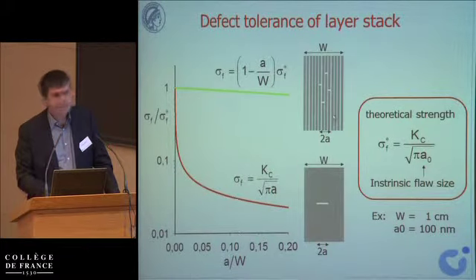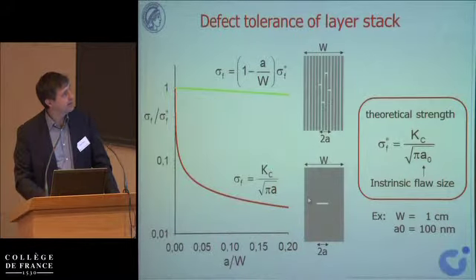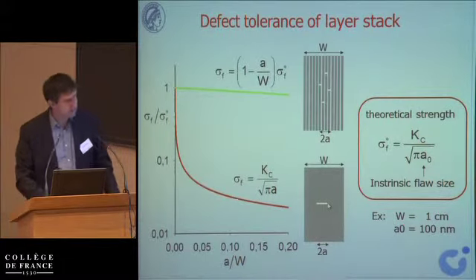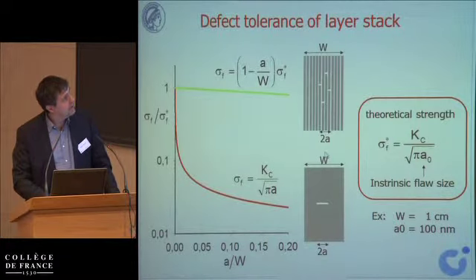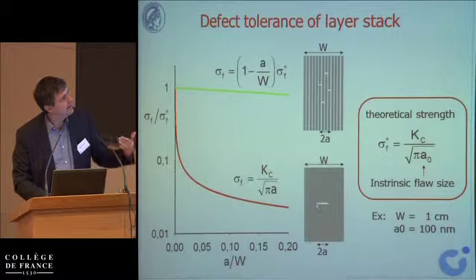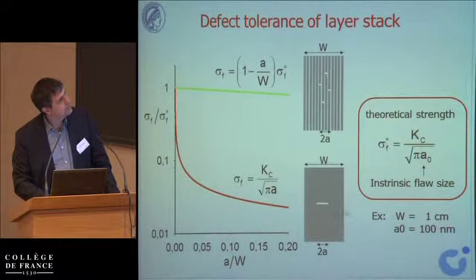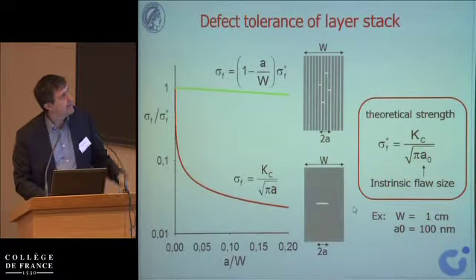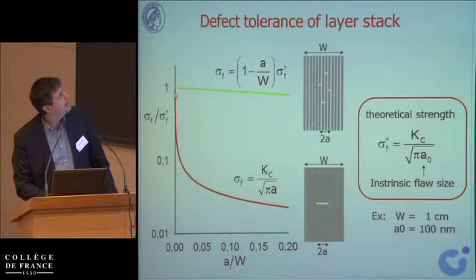That's something one of my colleagues in Leoben has done recently, and he's shown that indeed you get a dramatic increase in strength. So here is the plain material. If you put a crack in this plain material, there's one problem that everybody in material science knows: when you pull on this, you get an increase of the stress at these tips, which is given by this equation, where the increase in stress at the tip goes with the square root of the size of the crack. And that's a problem because if the stress here is larger than what you're applying, then it will make the crack propagate. And then you get this very nasty behavior that when the crack grows, the strength comes down.